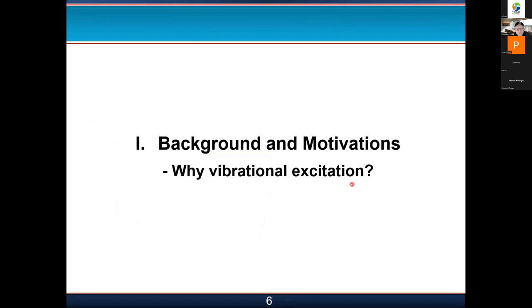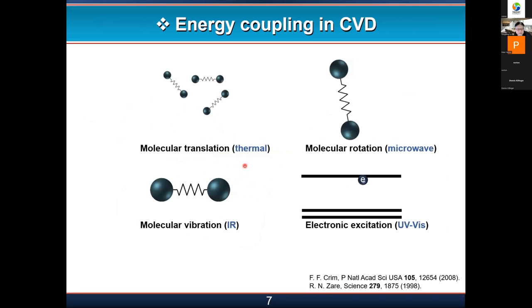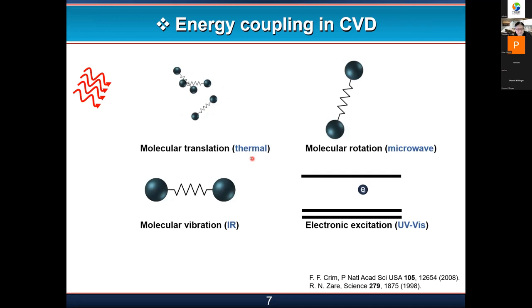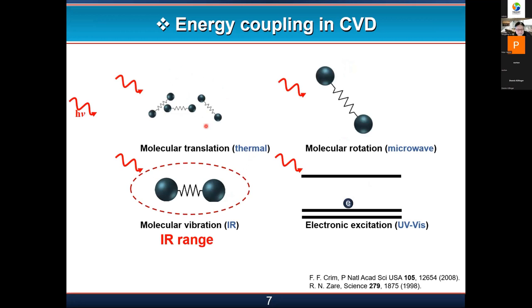So the vibration excitation is the approach we use to control or to improve the diamond growth. In terms of a chemical system, we have different energy levels. They can be translational, rotational, vibrational, and electronic. Certainly, electronic excitation is probably more effective in driving chemical reactions, but usually the lasers in visible or UV ranges are more expensive, and the powers are not very high. So we use the molecular vibrational modes because we can use CO2 lasers. The CO2 lasers can give us very high power, 2 kilowatts, and also a certain level of wavelength tunability.